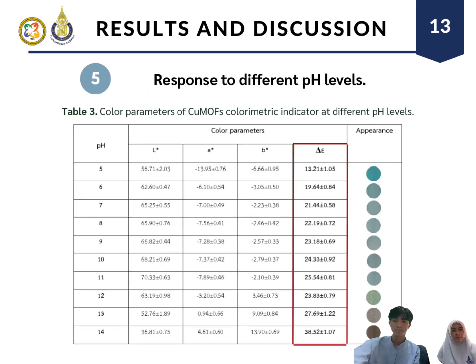For testing the response to different pH levels, as pH level increased, the delta E value also increased and the appearance of the indicator gradually changed from turquoise blue to gray and finally to brown at pH 14. This is because hydroxide ions interact with the copper site, changing the coordination environment around the metal center.